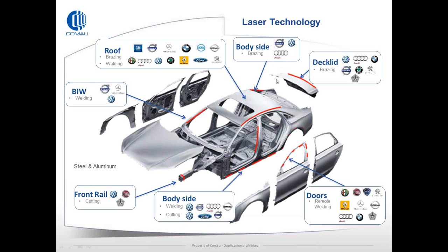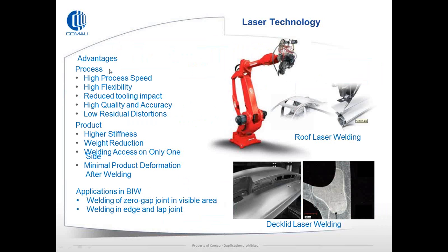Laser technology. Another process in terms of joining various materials. Here is just showing some of the different processes in terms of areas of laser welding, and not exclusive to this. So we've got remote laser on the door, brazing on the deck lid, roof joints can be brazed and welded also. This can be steel, aluminium, and becoming more commonplace with aluminium. Advantages: very high process speed, high flexibility, reduced tooling impact, high quality and accuracy, and low residual distortion into the actual product. Can offer higher stiffness, dramatic weight reduction, welding access only from one side, and minimum product deformation after welding because of the low impact.